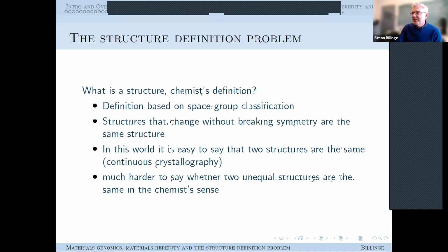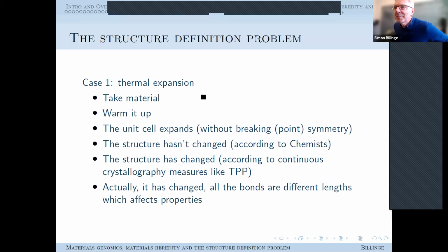Okay, let's do a little thought experiment here. Think about thermal expansion. So we'll take a material, could be nickel or chromium or something, and we warm it up. When we do that, because of thermal expansion, the unit cell expands, but it typically does so without breaking symmetry. So if it's a cubic unit cell, all three axes expand at the same rate, it's still a cubic cell, right? So from the chemist's point of view, the structure hasn't changed. In fact, the chemist would think you're a complete lunatic if you say that I take nickel, I warm it up 10 degrees, and now it's a different structure. They would laugh you out of the room, right? So from their point of view, the structure hasn't changed.